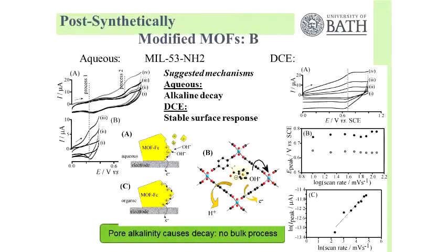The same for the other material, this is the aluminum MIL-53, which is a much more stable system. You have the ferrocene, you take one electron, and you have a proton removed from the cage. So you end up with a pore which is very alkaline, and the alkaline pore just dissolves the MOF.